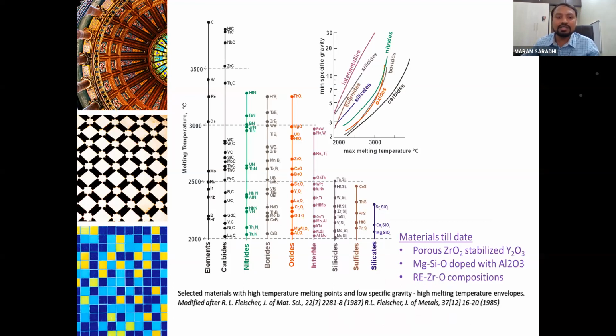By knowing the melting points of these materials, different classes of materials like oxides, nitrides, borides, and carbides, based on the temperature stability, we select the composition and we fine tune the composition and we make the coatings and we use that as a thermal barrier coating material in real time. Okay, this is how we work. So in our lab, my group is mostly working on zirconia based ceramics, magnesium silicate based ceramics and rare earth zirconium based ceramics.